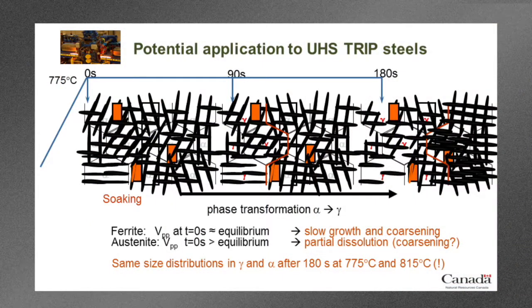And this could be explained by the following schematic. So what I'm showing here is the intercritical annealing cycle. So we're heating up at 5 degrees C per second up to, in this case, 775 degrees C, and I've drawn three diagrams of what could be going on at 0 seconds, 90 seconds, and 180 seconds of hold time. So we know at 0 seconds we're still ferritic. We have these big cementite particles, which I haven't drawn in here because they're not really essential for this discussion. And we have a mixture of titanium, vanadium carbonitride particles, which are these orange squares that I've put in here schematically, which are quite big, and they came from the hot band. And we have a distribution of very small vanadium carbonitride precipitates.